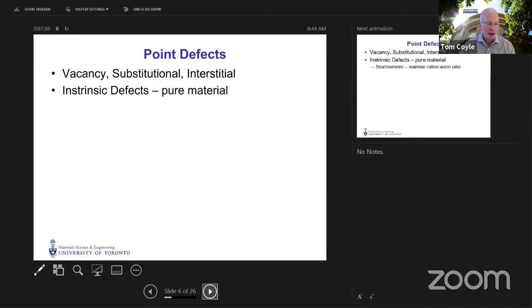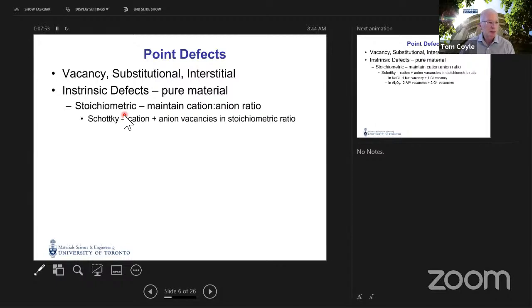So we have, as I have described, vacancies, substitutions, and interstitial defects. These defects can be intrinsic, meaning they occur in the pure material, and within a pure material, they can be stoichiometric, meaning that the cation to anion ratio remains constant. An example of this is called a Schottky defect. This is a combination of a vacancy on a cation site and a vacancy on an anion site, with those vacancies occurring in the stoichiometric ratio, so that the total number of cations and total number of anions remains in balance.